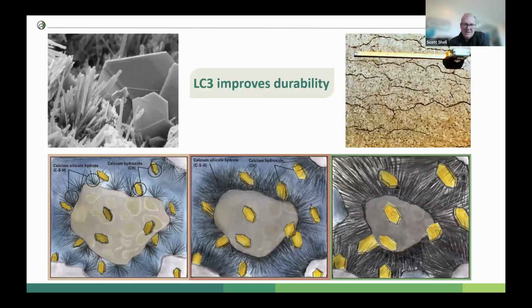One of the great characteristics of LC3 is that it significantly improves the durability. This is actually true of many SCMs, is that they make a better concrete. So on the upper left there, you see an electron microscope image of cement. The needles are the calcium silicate hydrate. On the bottom, you see a drawing of cement hydrating. You add the water to it, and these needle-like crystals start growing until they all interact, and that's when the concrete sets and hardens. All these interlocking needle-like crystals.